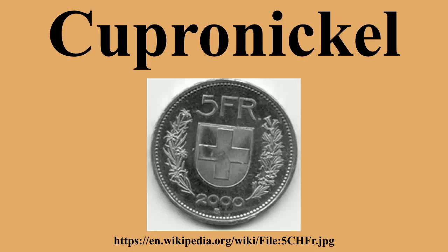The C71640 alloy tends to be used as seamless tubing and expanded rather than welded into the tube plate. Brazing requires appropriate silver-based brazing alloys. However, great care must be taken to ensure that there are no stresses in the Cu-Ni being silver brazed, since any stress can cause intergranular penetration of the brazing material and severe stress cracking. Thus, full annealing of any potential mechanical stress is necessary.